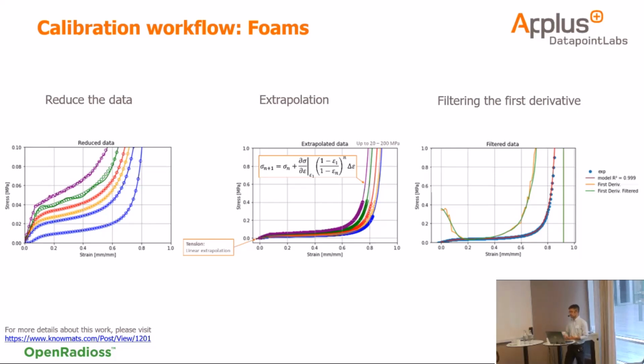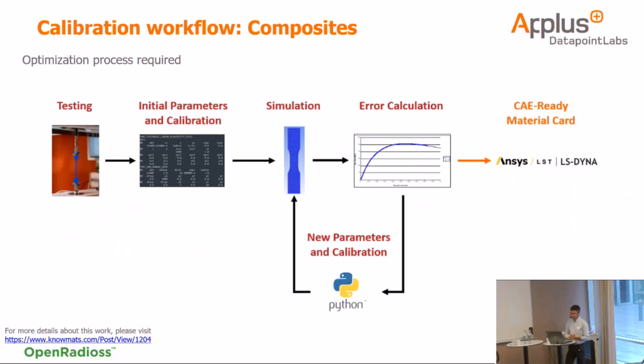And then you integrate this curve again, so you can get the red one, which is almost the same curve as the dotted line. So in this way, we can achieve a good stability for the model, particularly for foams and the large deformation of the elements. And finally, for composites, it's kind of a mix between both.